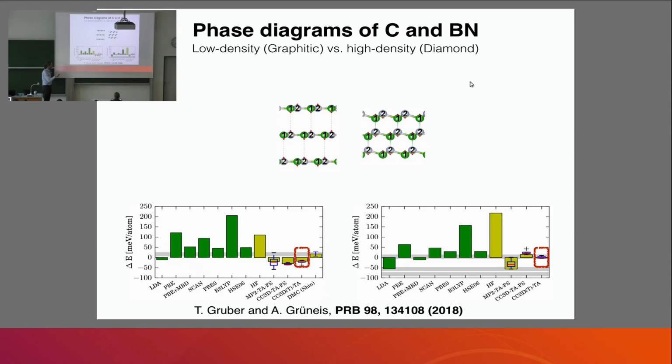These are the results that we get for the quantum chemical many-electron theories. Hartree-Fock theory would not even predict graphite to be the most stable phase, but really just a single graphene layer, because it doesn't account for any dispersion interactions. So the zeroth-order approximation is a very bad starting point, much worse than LDA. But then as you move on to MP2 and coupled cluster theories, you see that there is at least a more systematic approach. The result on the level of coupled cluster plus perturbative triples is not in perfect agreement with experiment, but it's clear that there is at least some safety about this result.